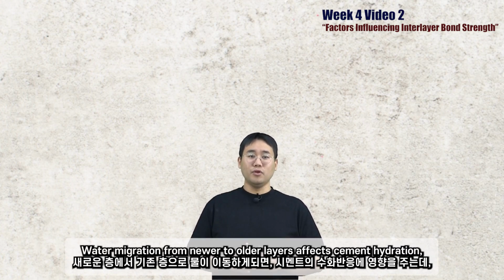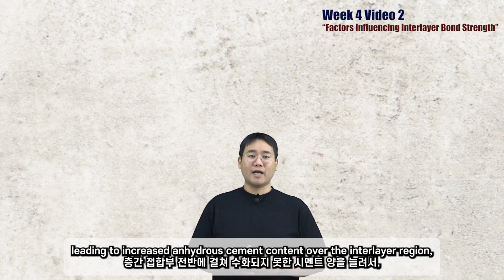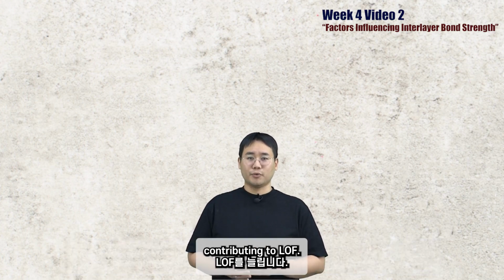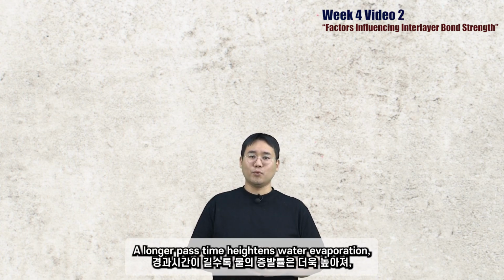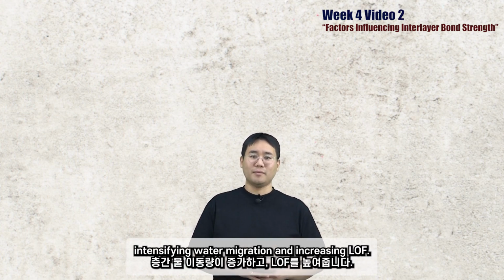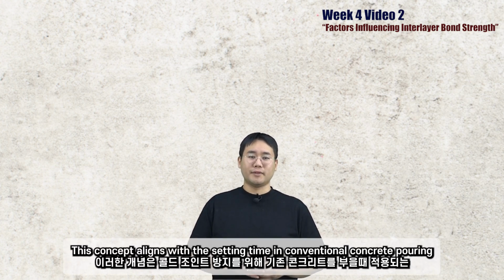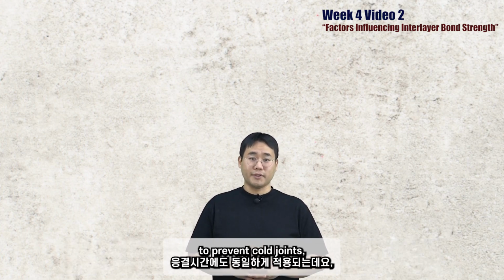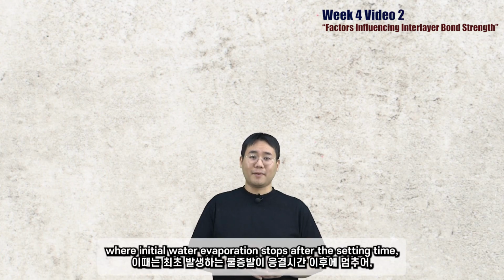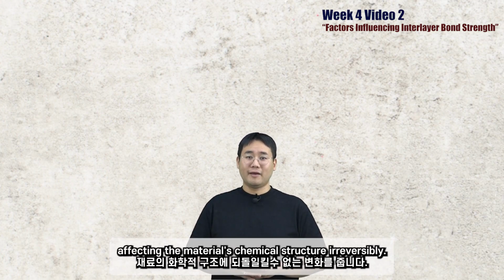Water migration from newer to older layers affects cement hydration, leading to increased anhydrous cement content over the interlayer region, contributing to the lack of fusion. A longer pass time heightens water evaporation, intensifying water migration, increasing lack of fusion. This concept aligns with the setting time in conventional concrete pouring to prevent cold joints, where initial water evaporation stops after the setting time, affecting the material's chemical structure irreversibly.